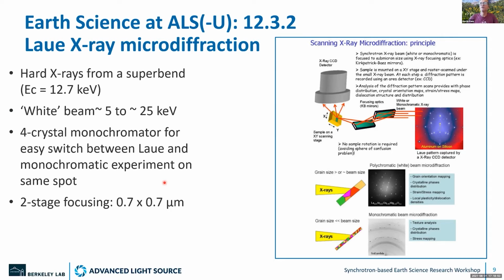At each spot of the sample, which can be scanned very fast underneath the beam, a sub-second exposure is produced, and this allows Nobumichi to create maps of Laue diffraction patterns in a millimeter range with 1 micron resolution. The data that can be gained from a Laue diffraction pattern are grain orientation maps, crystalline phase maps, deviatoric strain maps, and also maps with information on plastic deformation. The obvious condition for this experiment to be successful is that the grain size needs to be of the order of magnitude of the X-ray spot size or bigger. That means around 1 micron.